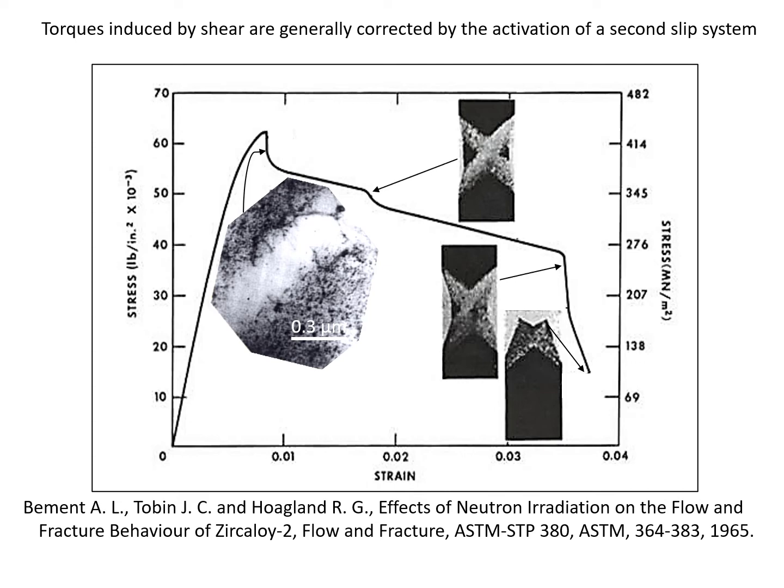But what happens is that the gliding dislocation, like this, interacts with the loop, subsumes the dislocation loop into the extra half plane, if you like, of the dislocation, and carries on and essentially sweeps the loops out of the material. It only applies to loops because it has to be a loop which can essentially conform with the Burgers vector, either by dislocation reaction or by having exactly the same Burgers vector as the gliding dislocation. When that happens, you create this softer channel.